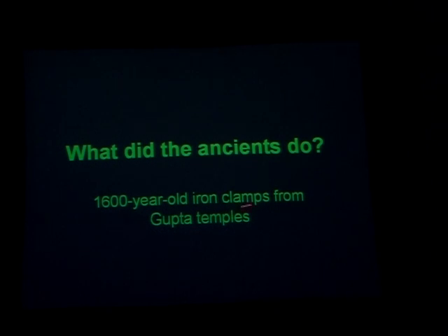I got hold of iron from Gupta temple at Devgarh, 1600-year-old iron, and put it into metallography. Oberhoffer's reagent, which will reveal phosphorus content. You can see the grain boundary has been relieved of phosphorus. They have done something to the material. The grain boundary does not contain phosphorus. Therefore, the iron is going to be ductile.